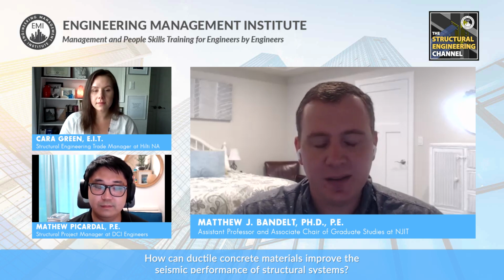Recently, my research group has been using numerical models to help understand how we can design entire buildings with ductile concrete systems, and we've found really promising results. For example, we found that you can reduce the probability of collapse under a maximum considered earthquake by as much as 40% when you use these ductile concrete materials. And you get this advantage while actually using less concrete material, because the strength is so high you can reduce section sizes. So you can have increased performance while reducing the amount of concrete you're using in a building. These have been used in select applications in the field, but I think that will grow over time.